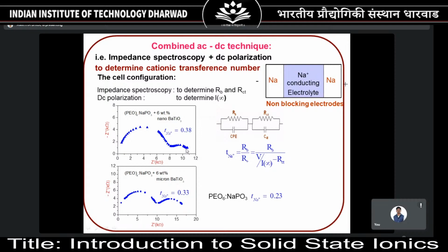Okay, and thereafter you subject it to DC polarization. That means you connect it to a voltage source, and you see how the current is depleting. Initially, the current value is high because that is a combination of both electronic and ionic contributions. Since it is an ionic conductor, polarization takes place over a period of time. The current will be decreasing. Earlier, it may be 5 milliamps. After waiting for about 12 to 18 hours, that 5 milliamps current would have reached the microamps region. That means the current has decreased, resistance has increased.